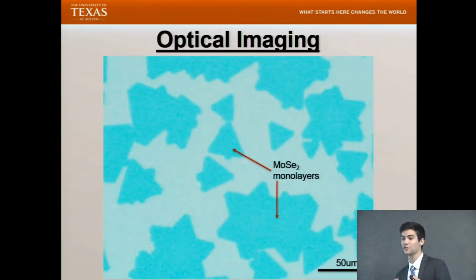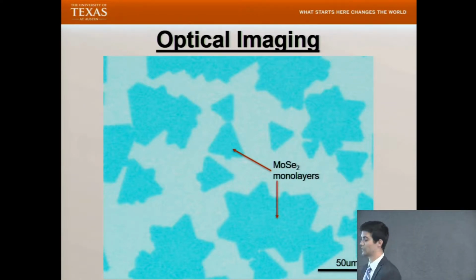So for the first step of characterization, I used an optical microscope, basically just to see if anything had actually grown on my sample. I also used it to find potential monolayers that I could analyze further. And this image is an example of an optical microscopy image, and it just illustrates what MoSe2 monolayer domains look like. You can see those here.